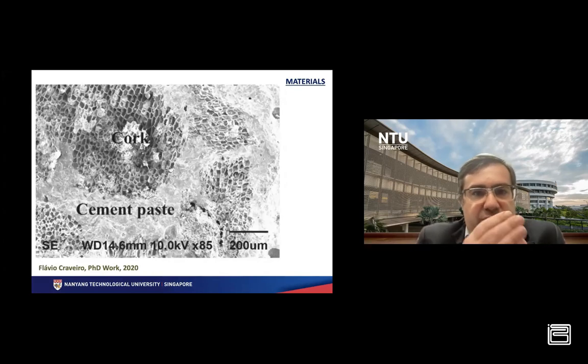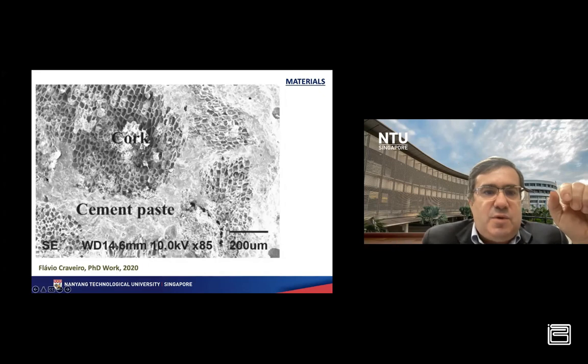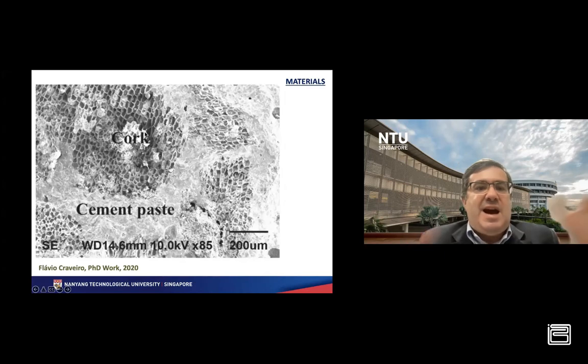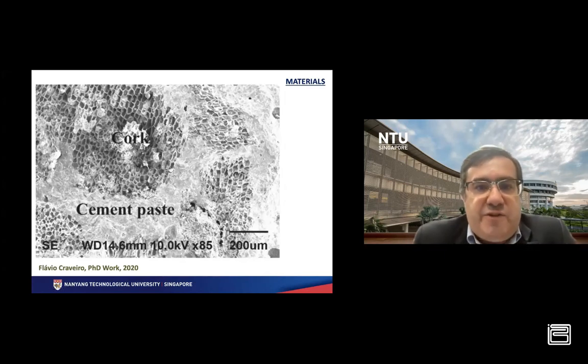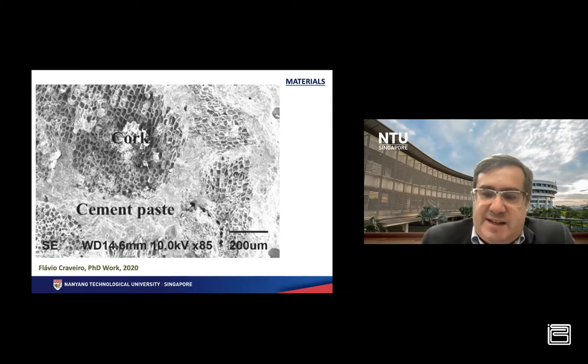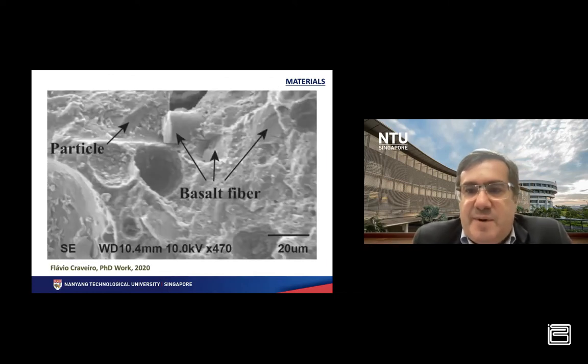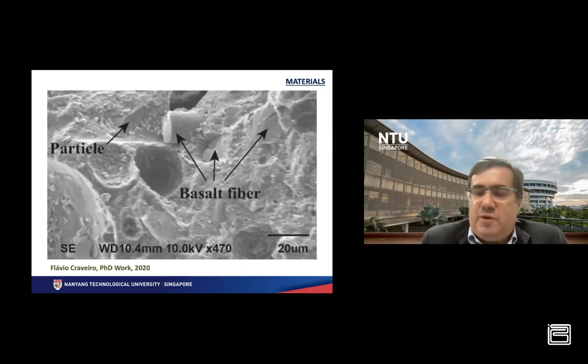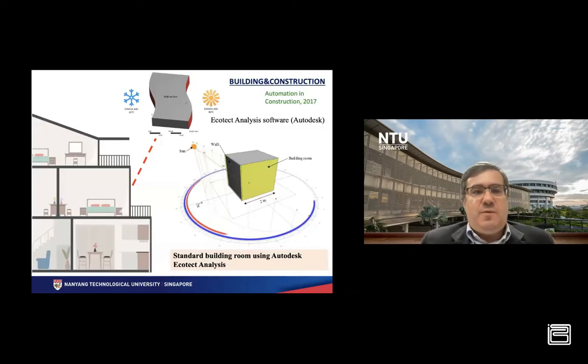But before that, let me show you some scanning electron microscopy images of parts of our printed structure. So this is some cork particles embedded in a cement paste. And as you can see, even after printing, we keep the honeycomb structure of cork. We tested other materials like basalt fiber. So we are exploring a range of materials for concrete printing. As I mentioned, the advantage of cork was to improve the thermal performance of our construction elements.